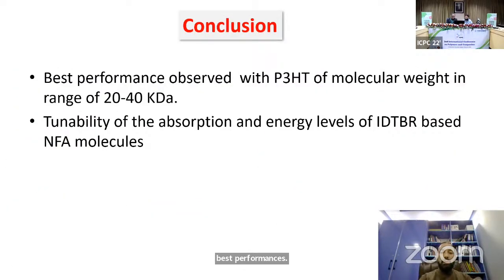Finally, the conclusion. We have seen the best performance from the poly-3-hexylthiophene with a molecular weight range of between 20 to 40 kilodaltons. And we also have seen that we can tune the absorption and energy levels of these non-fullerene acceptors, which can help to improve the solar cell efficiencies.